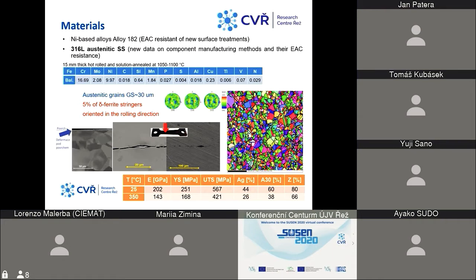So I will be more focusing on the stainless steel part, and I will show you some results we gained during these years with my colleagues. So we use the 15 millimeter thick hot rolled and solution annealed plate of the stainless steel. Here you can see the microstructure of the plate. It has an average grain size of about 30 micrometers. It also has delta-ferrite stringers distributed along the plate in the rolling direction. And here you can see some mechanical properties of the plate.